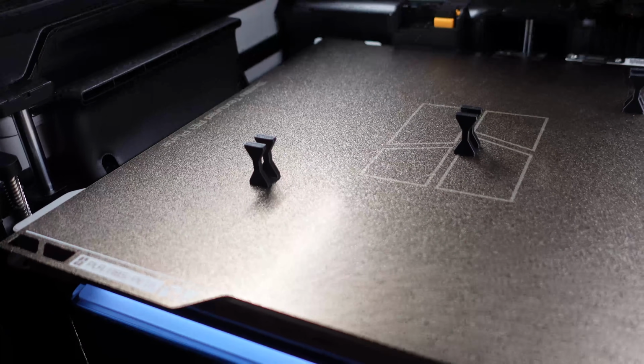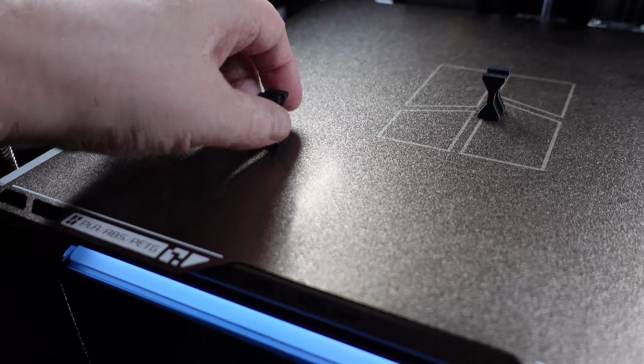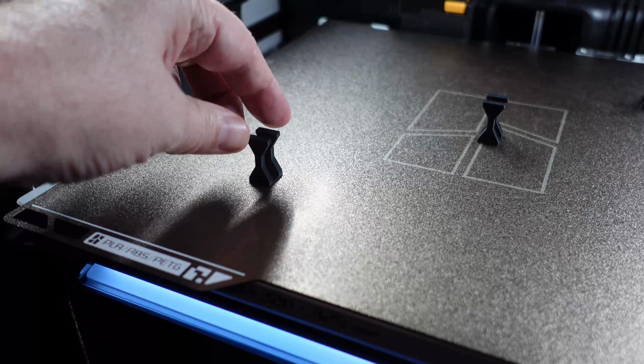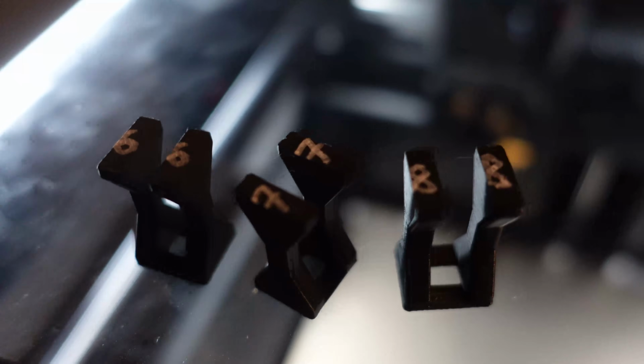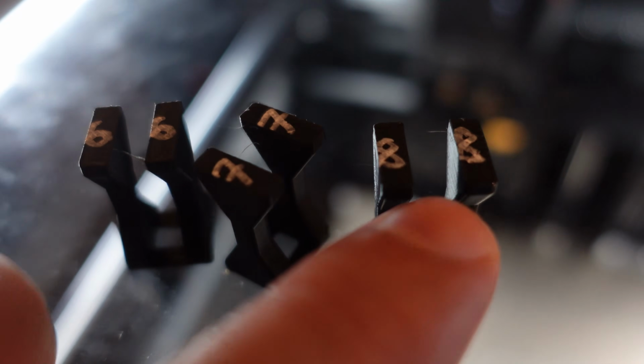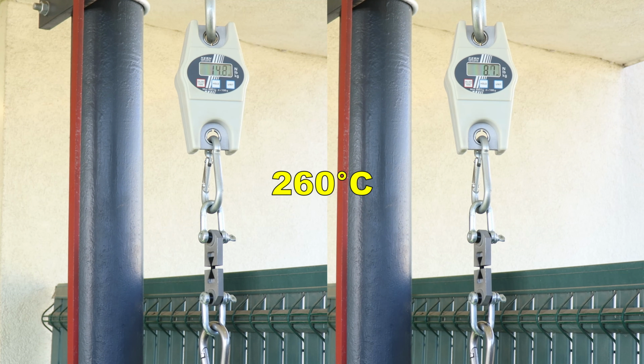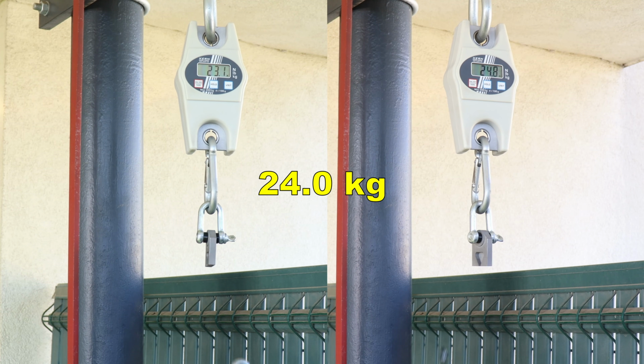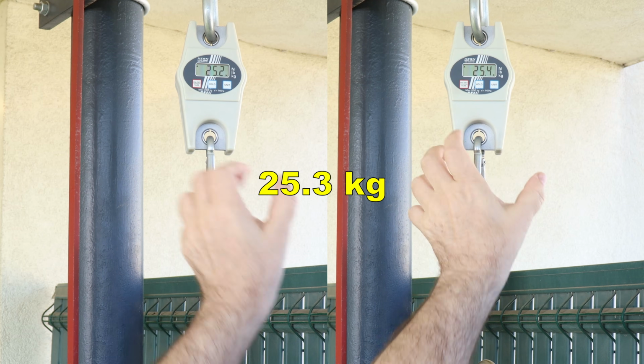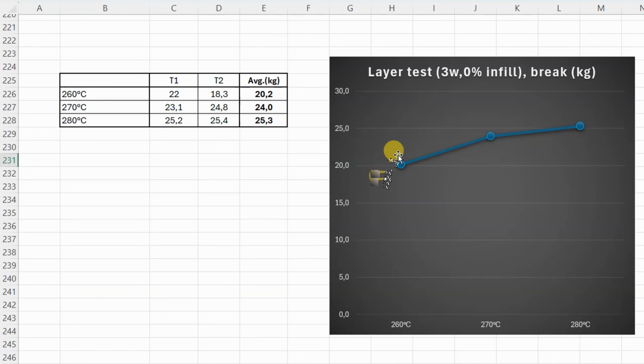Quick check of the bed adhesion. Oh, I think I will increase the bed temperature. They are marked 260, 270 and 280 degrees Celsius. The improvement is obvious, but the improvement between 260 and 270 is bigger compared to 270 and 280, and all test objects are reprinted on 280 degrees Celsius.